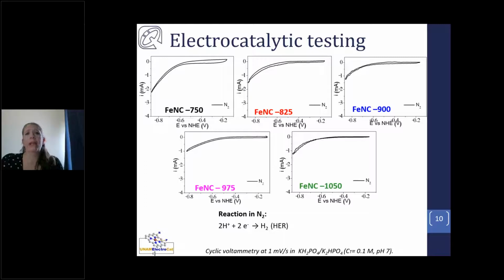Once we had characterized these materials, we started doing some electrochemical testing. The first electrochemical testing that we normally do is cyclic voltammetry, where we compare how the reduction currents are in the absence of CO2 and in the presence of CO2. So what I'm showing you here is just the current in an aqueous electrolyte of the 5 catalysts saturated with nitrogen. And we see that in all cases, we have some reduction current, which can be attributed to the competing process of the hydrogen evolution reaction.